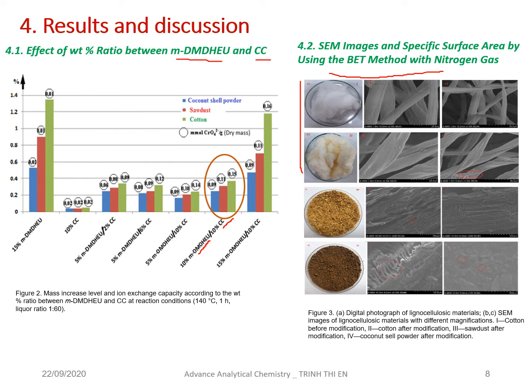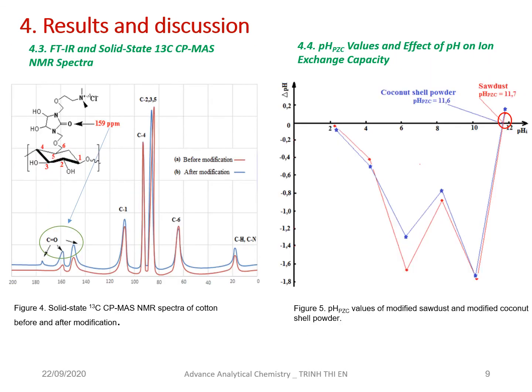And this is the cotton before modification, at different magnifications of the same image, and the cotton after modification. It creates the crossing or bridge here. And the sawdust and the coconut shell powder before modification show the clotting here, and some clotting here. And this material was successfully synthesized, as examined and checked by